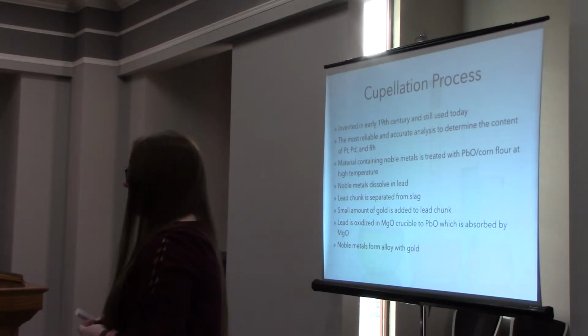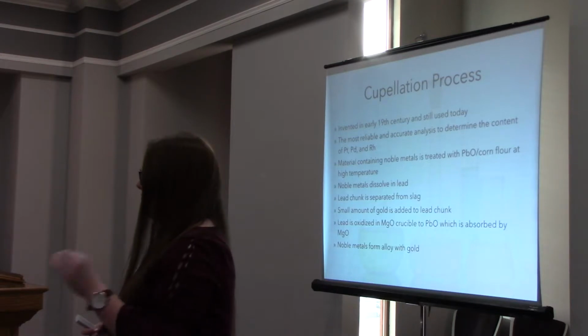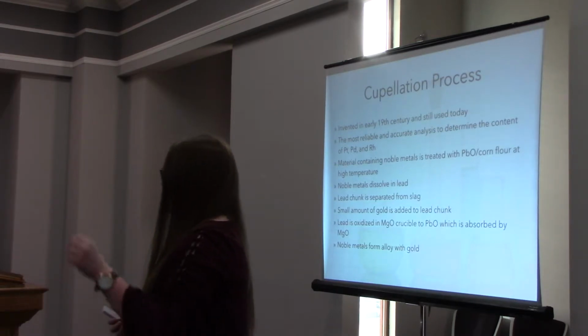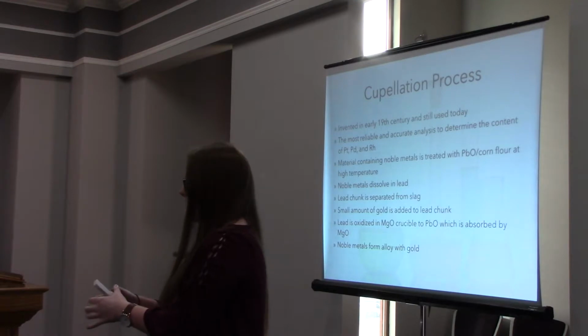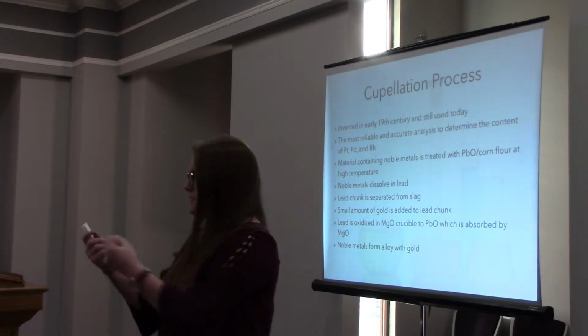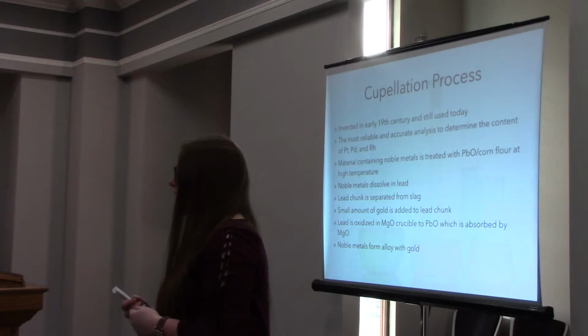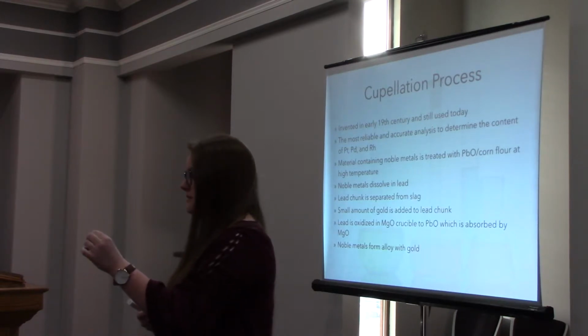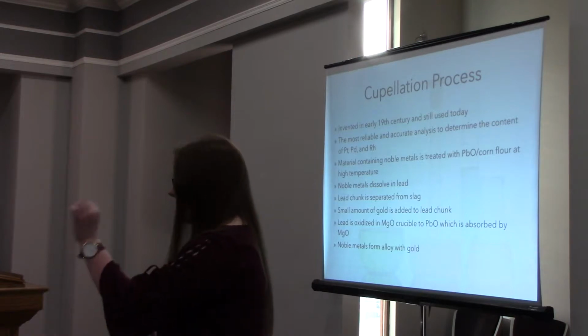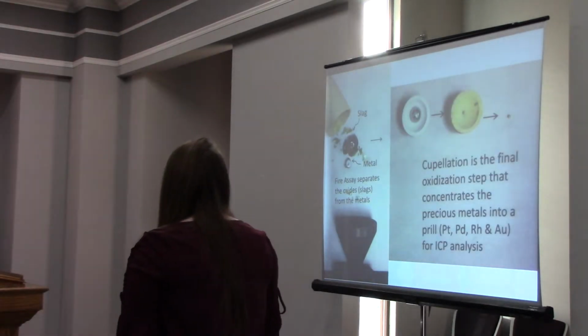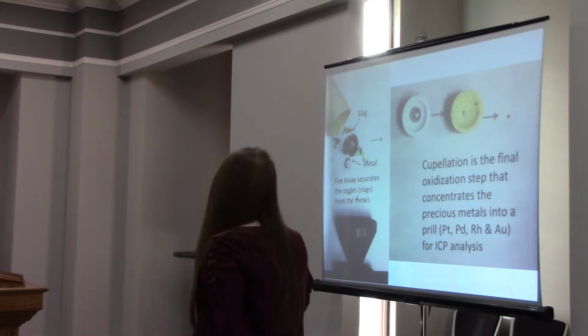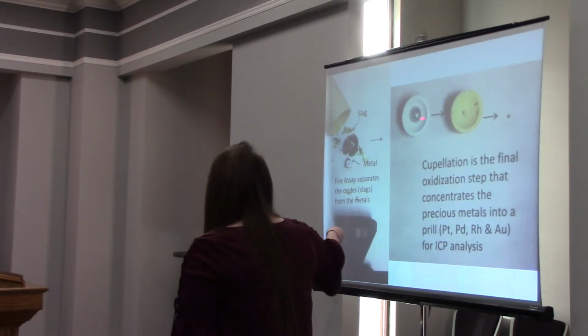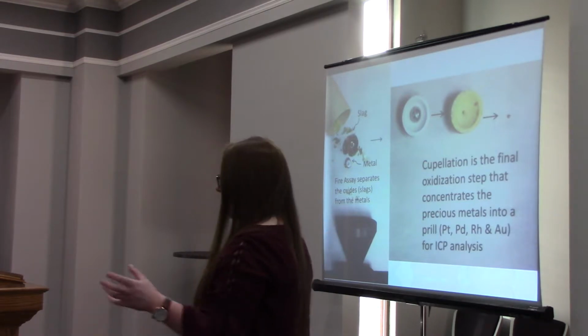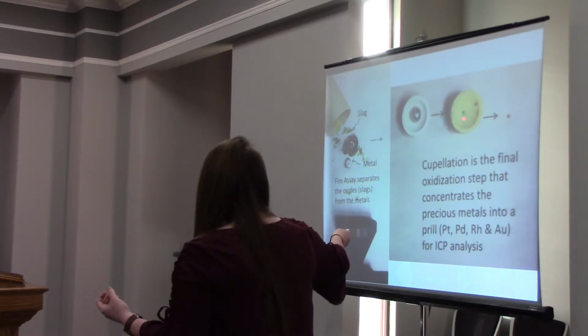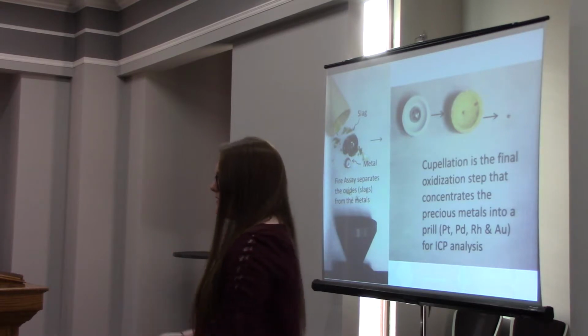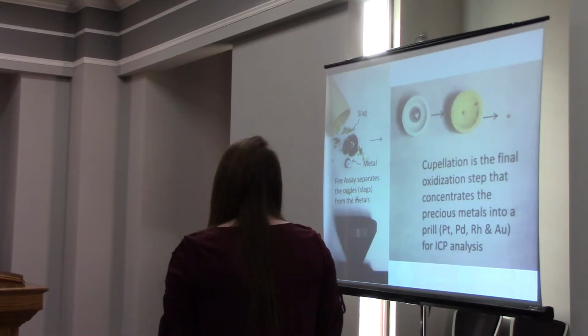And a small amount of gold is added to the lead chunk, and then the lead is put into this magnesium oxide crucible. And the magnesium oxide crucible will suck all the lead oxide out, leaving just the noble metals in a little pellet. So here's the process, and this is the extra slag that they separate out. That's the little lead. You can put it in the white thing, which is the magnesium oxide crucible, and it turns yellow because lead oxide's yellow. It sucks out all the lead oxide, just leaving the noble metals in that little pellet.